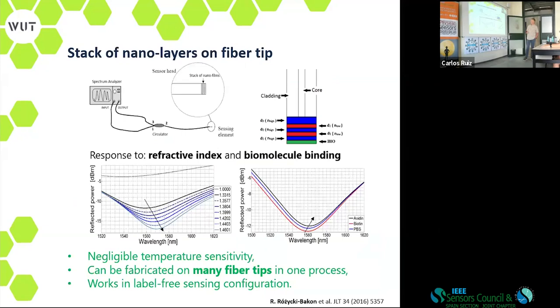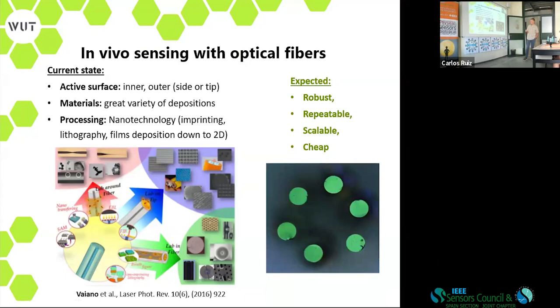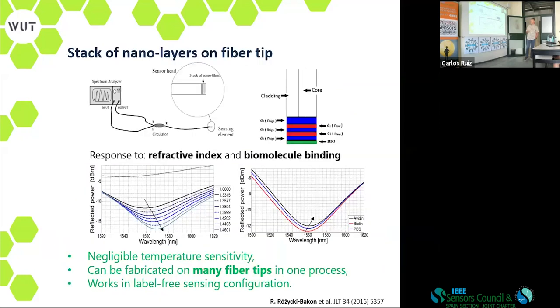Okay, so just to show you this. These are the surfaces of optical fibers changed with some thin films, and this is just a sample. We can manufacture six of them here, but I will show you later many of them the same way. So we started with many films on the surface. We just thought that this would be a good solution, and it worked. It worked for refractive index. It worked for sensing of some biomolecules on the surface, and it's scalable. Many hundreds of fibers can be processed the same way, so that's good, but not sensitive enough.